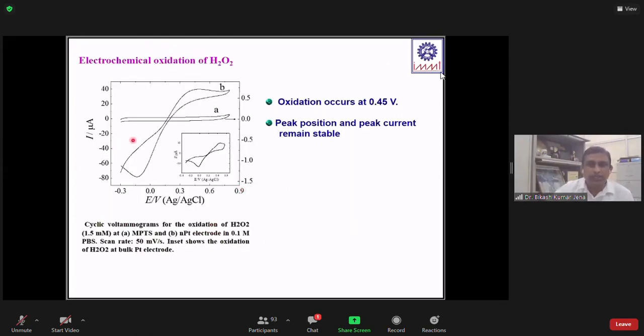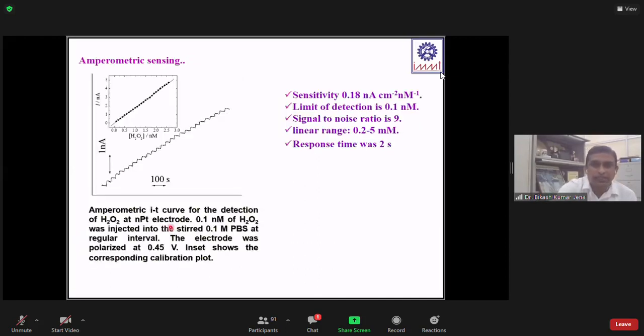So we use this nanoparticle for sensing of hydrogen peroxide, because for oxidase-based enzymes, hydrogen peroxide detection is very much essential. We did electrochemical cyclic voltammetry to understand at what potential hydrogen peroxide is getting oxidized. We observe that it's 450 millivolt, like 0.45 volt. And using this, we develop an amperometric technique by holding the electrode at that potential. When you inject hydrogen peroxide, that is reflected as an increase in the current. So you put the hydrogen peroxide into the solution, where your nanoparticle modified electrode will be there. When you put the hydrogen peroxide, it quickly oxidizes and gives the change in the current.